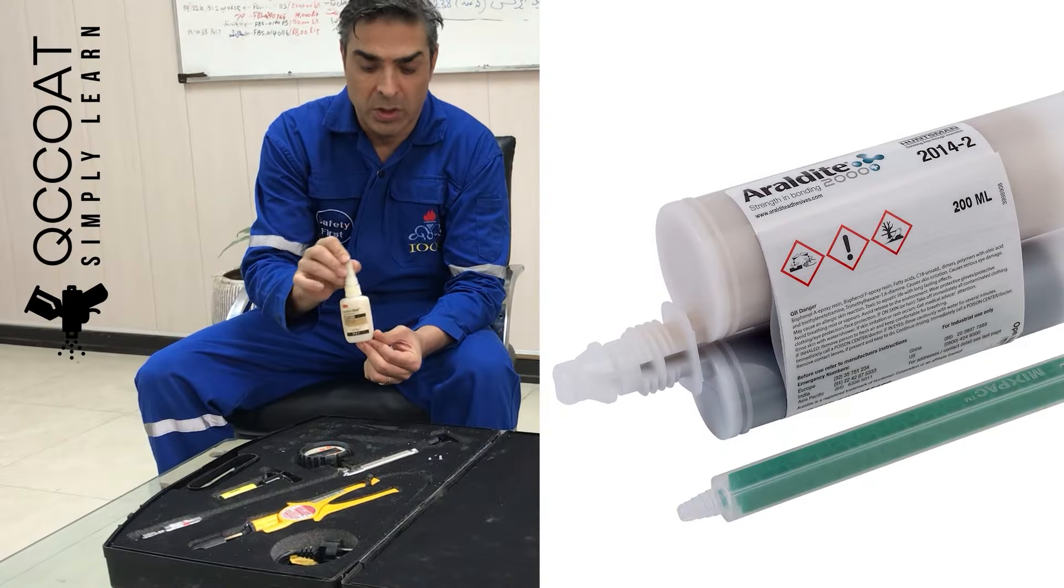Enter the force uniformly up to 1 MPa per second. Write the amount of force that caused the separation or the maximum force that was applied and the paint did not separate.